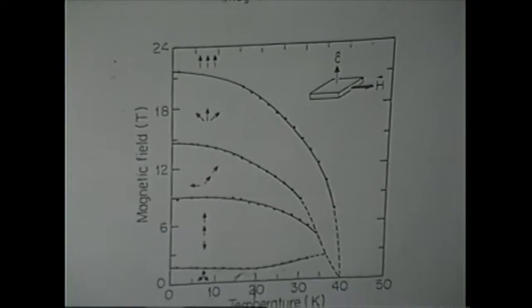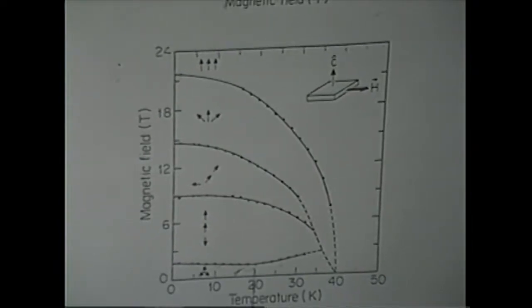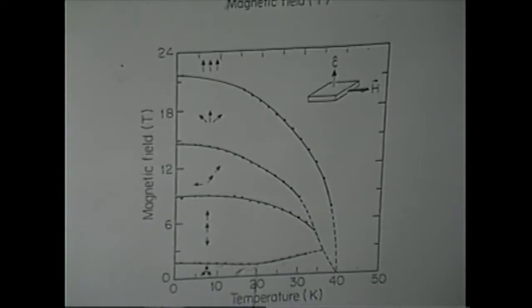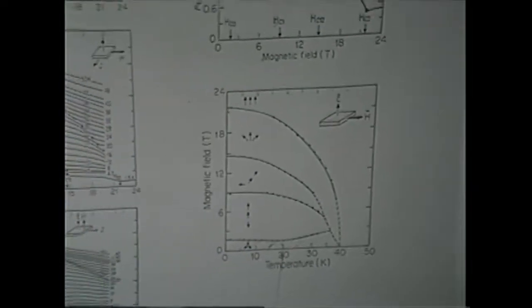That's simple enough, but what is the explanation of what the spins are doing? That's a little bit more difficult. And there were two things that were done here. There was a model calculation done by Date in Japan, and we did a Monte Carlo simulation which identified what these various spin states are. And there was a little bit of new physics that came from this, a little bit unexpected. In magnetism course, in basic solid state course, we always teach that the Heisenberg Hamiltonian that controls the magnetic interaction in a magnetic system is a quadratic form between adjacent spins, and then we go second neighbors, third neighbors, etc. But with a Hamiltonian like that, you get nowhere with this phase diagram. You need to have some higher order terms, these biquadratic terms, and four-ring spin terms that show up in a triangular lattice.